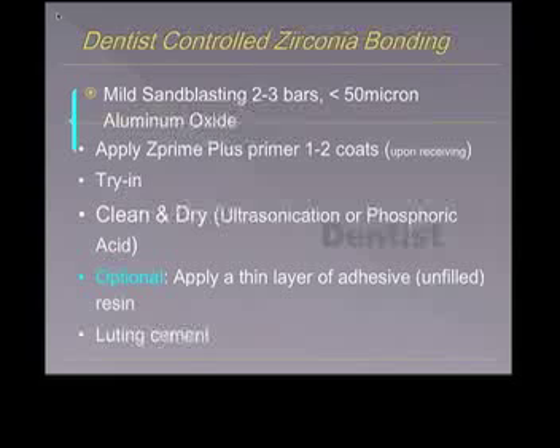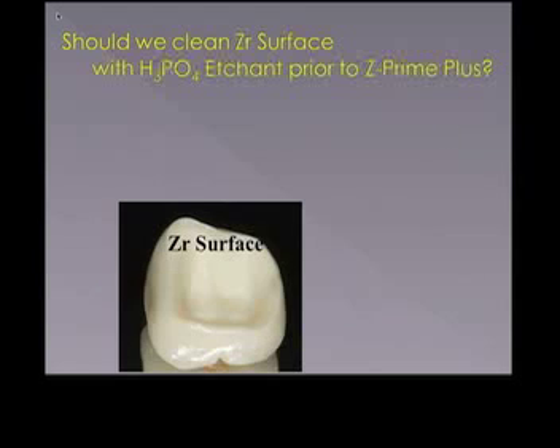So applying Z-Prime Plus to the restoration prior to the try-in forms an instant covalent bond. Remember, we like covalent bonds with the sandblasted exposed oxide receptor surface sites found in zirconia, aluminum, and metal. Decontamination post-try-in with alcohol, ultrasonication, or phosphoric acid will not affect previously applied Z-Prime.